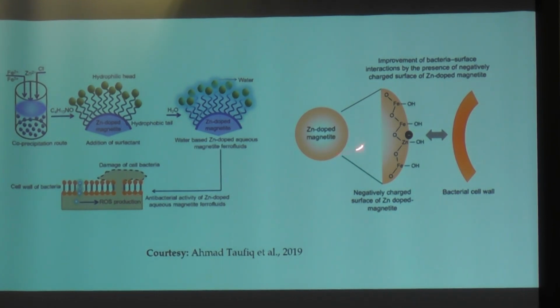We propose something like this. If we dope zinc into the magnetic nanoparticle, the data will be like this, because the cover of the magnetic particle, the Fe2+ and 3+ and Zn, will be minus of OH. So the bacteria cell will be attracted and also killed easily by an external magnetic field. Besides giving magnetic nanoparticles, we also make an external treatment using an external magnetic field. Based on the data, it can kill the bacteria more significantly than the conventional one.